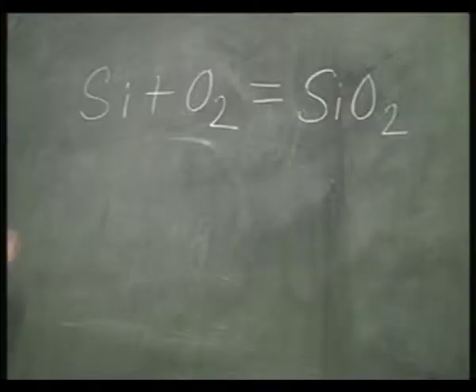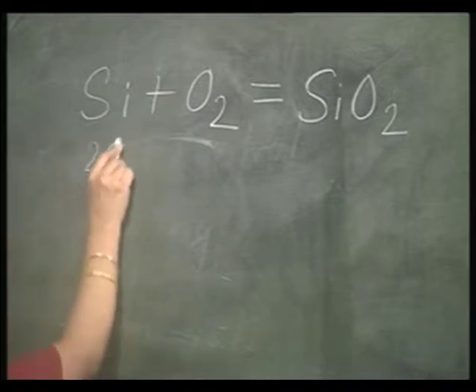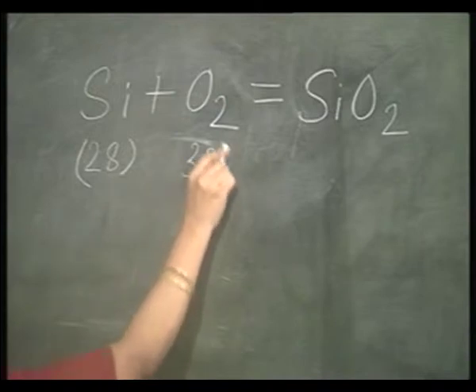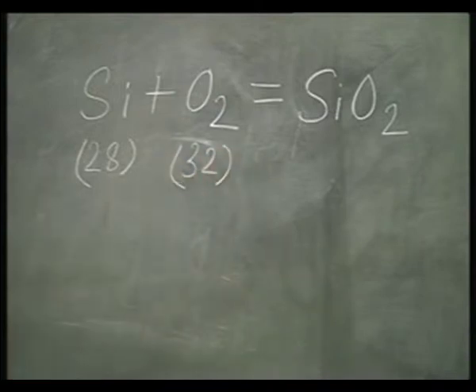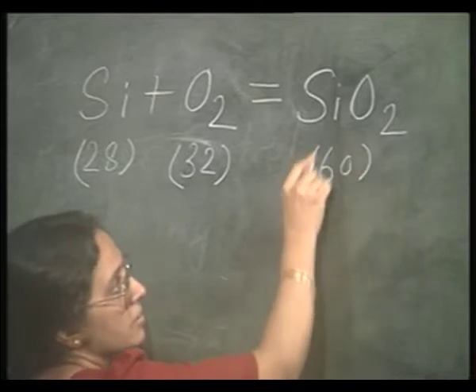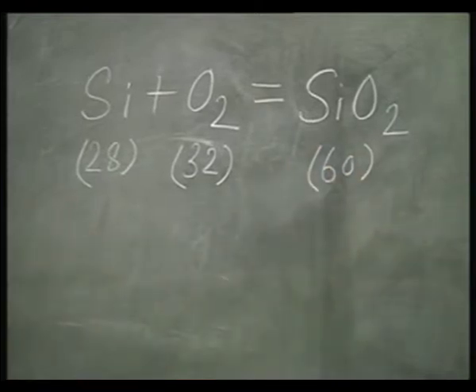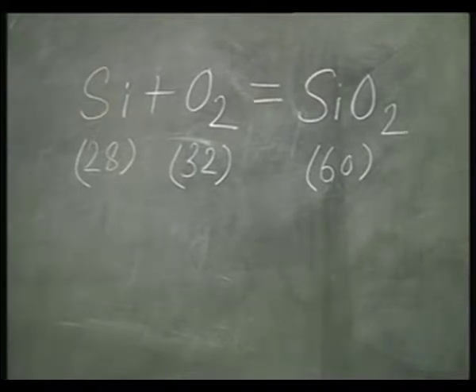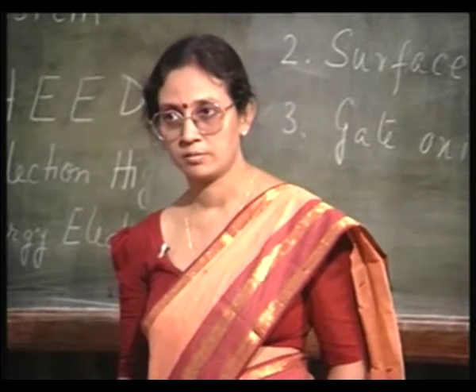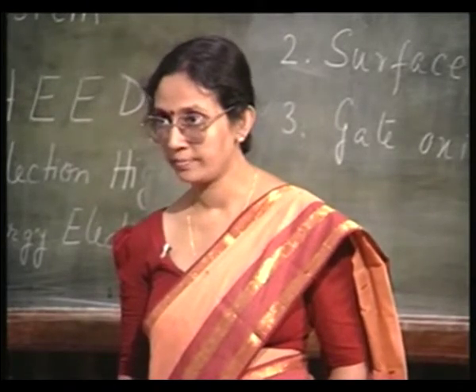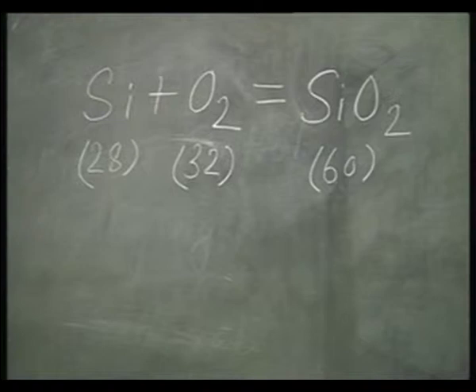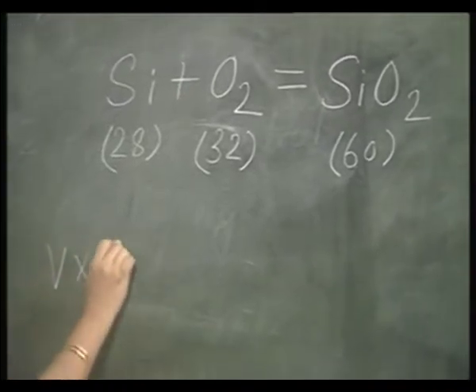The molecular weight of silicon is 28. And this is 16 plus 16, that is 32. Therefore, the molecular weight of silicon dioxide is 60. So, going by this reaction, I can say that 60 grams of silicon dioxide will be formed by consuming 28 grams of silicon, isn't it? Now, what is 60 grams of silicon dioxide? 60 grams of silicon dioxide actually means the volume into density.